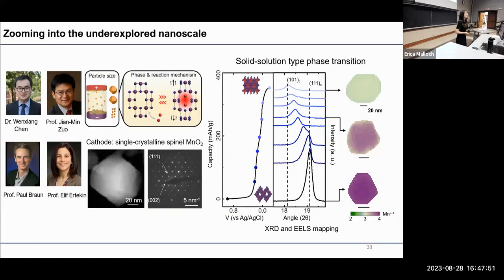So in this particular system, we use single crystalline spinel lambda manganese oxide particles as the cathode material for a magnesium ion battery. This particle is single crystalline to begin with, which can be told from its very nice faceted shape and only one single set of electron diffraction pattern. Then when we run the electrochemical cycling, which basically means we're forcing magnesium ions to diffuse in and out of the cathode particle.